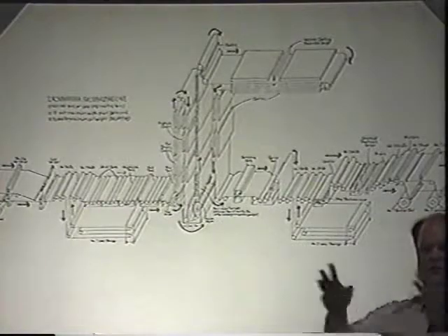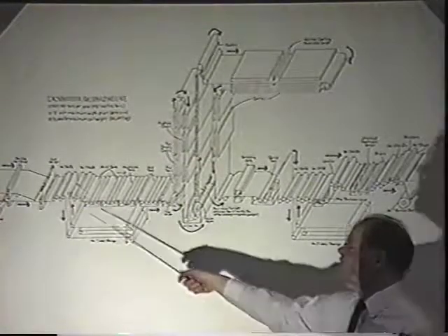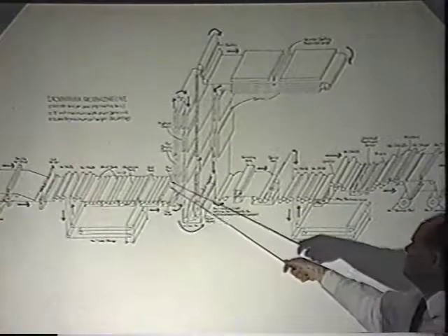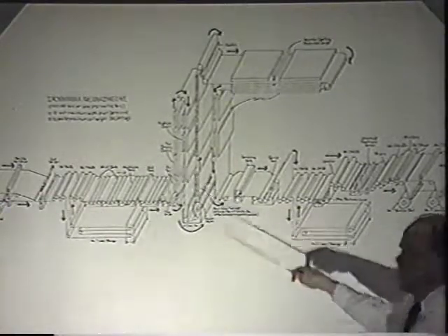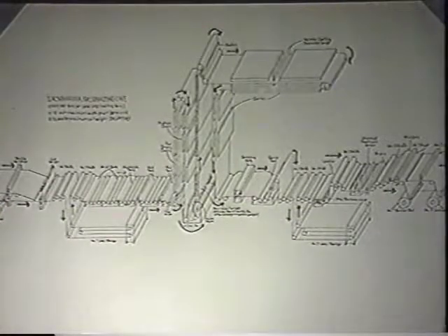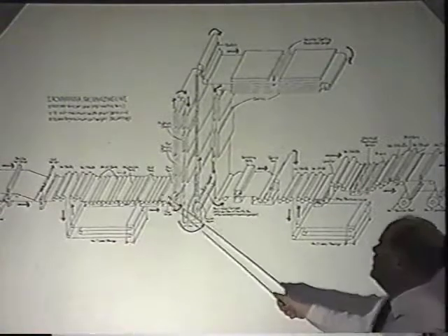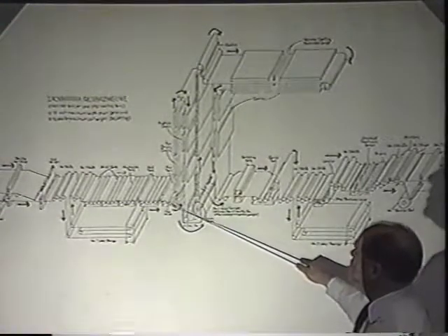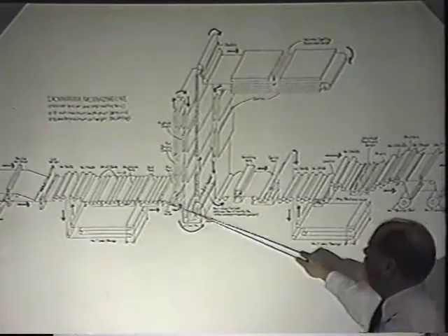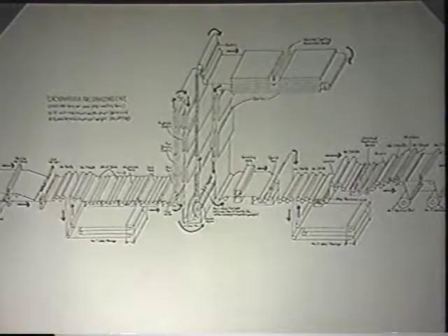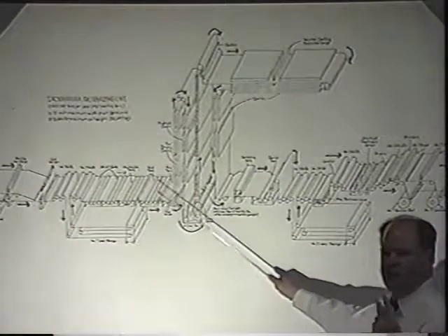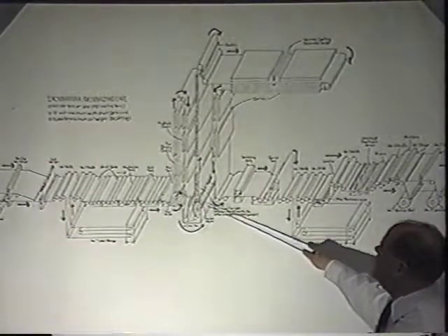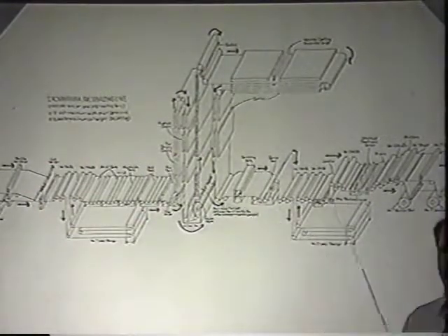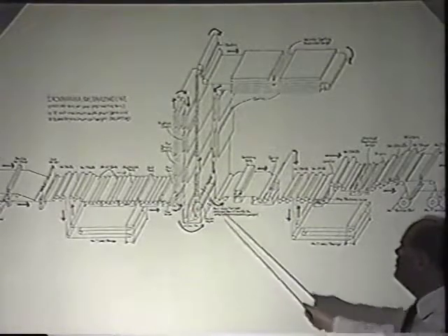They have to kind of send it to two other places, get it annealed, get it temper rolled, and then bring it to their line. So they don't have the annealing furnace, so they're not going to be able to heat it up to 860 degrees. We actually have to cool ours down, but they can't heat theirs up because it would change the properties they made back in batch anneal. So what they do is apply a flux to it, hence the name cold flux line. It's actually like a welding flux, ammonium chloride kind of solution that's going to attach to the strip. They just kind of put it through a little dip tank, and that's going to help the zinc stick. That's going to form the bond between the zinc and the base metal.